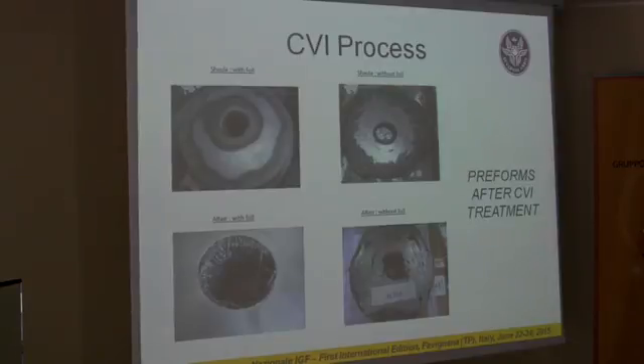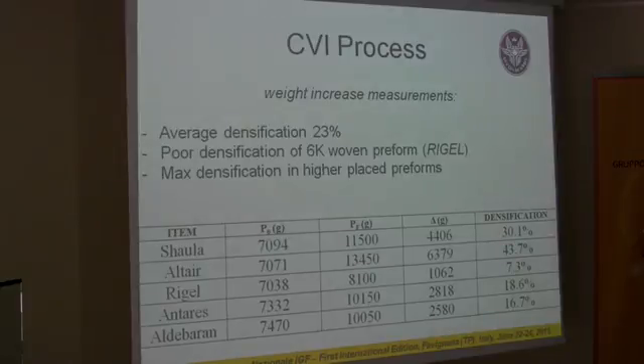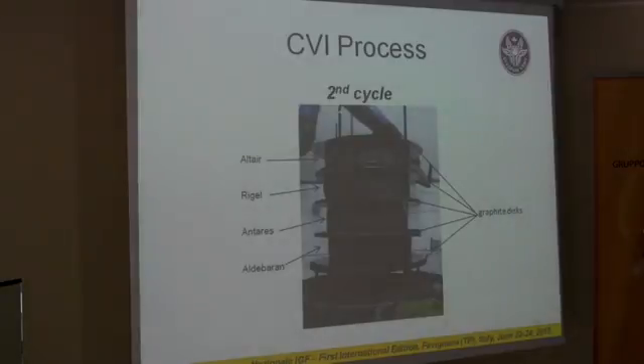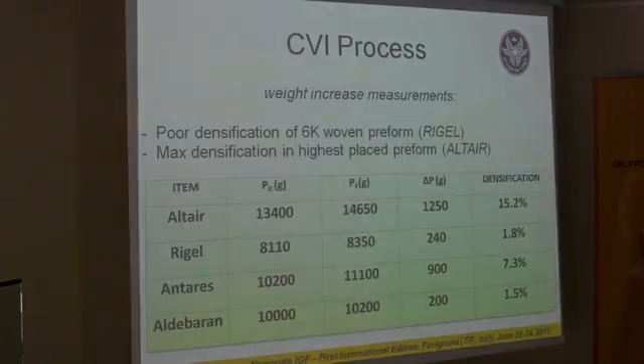This is a picture of some items just after the first cycle of infiltration, and here are the first results of the total weight increase. It can be seen that poor densification occurred for the 6K woven preforms, while better results are obtained for the top placed preform inside the oven. After the first cycle, one preform was removed for the detailed densification analysis, thus only 4 were put again inside the oven with the same arrangement. And these are the results of the densification after the second cycle, which stress again the bad results obtained for the 6K woven preform and the maximum value of densification in the highest placed preform.